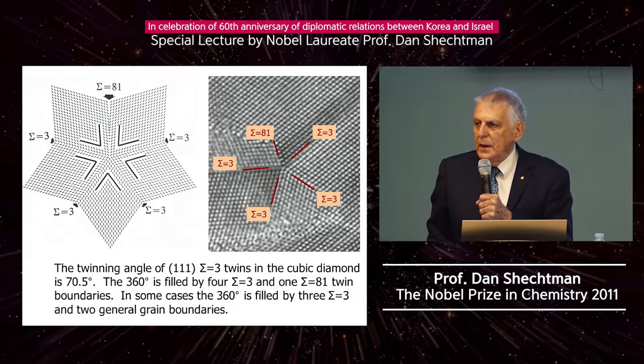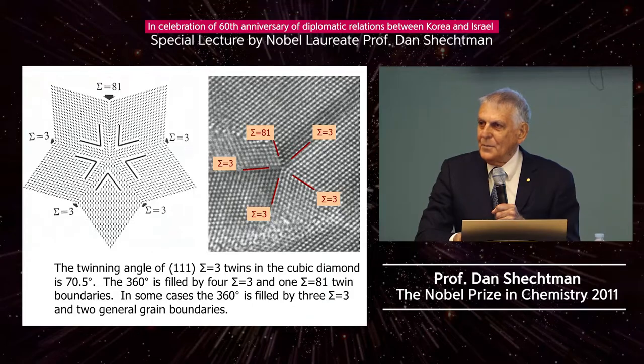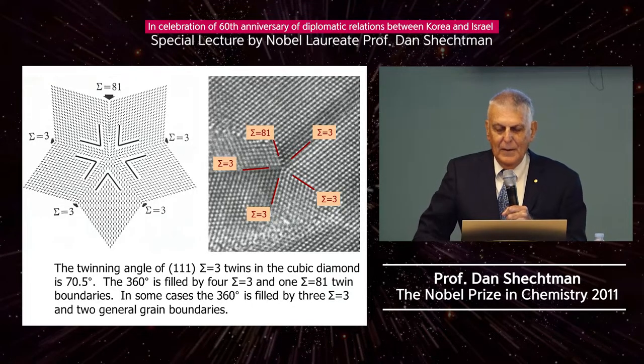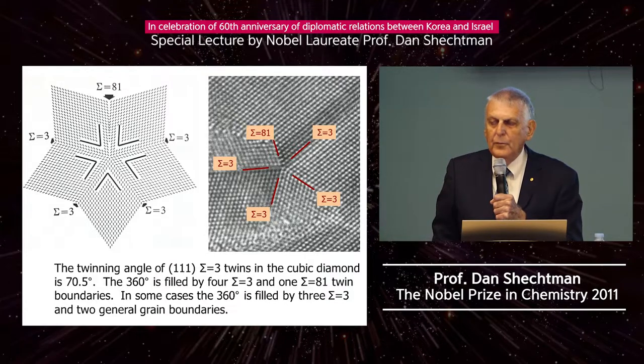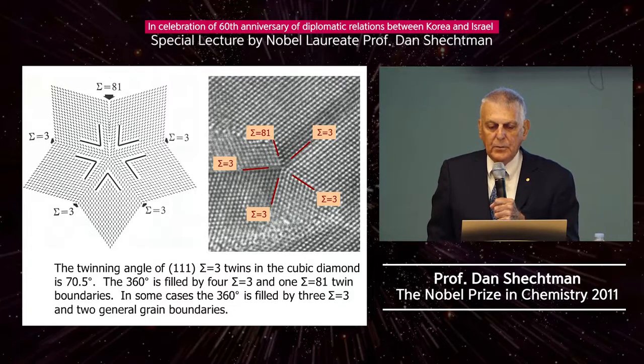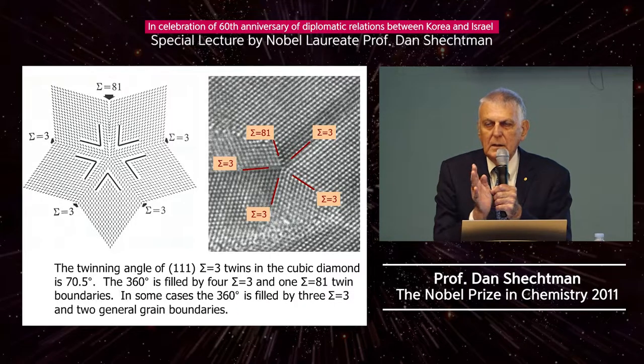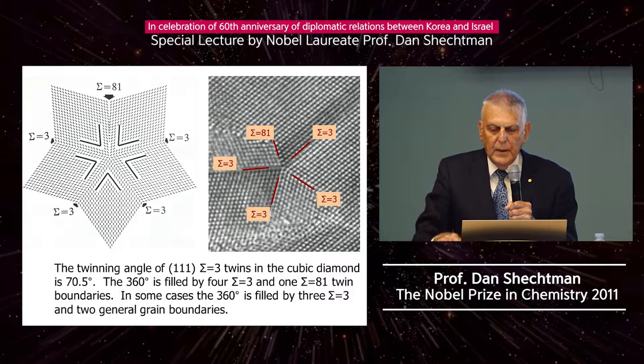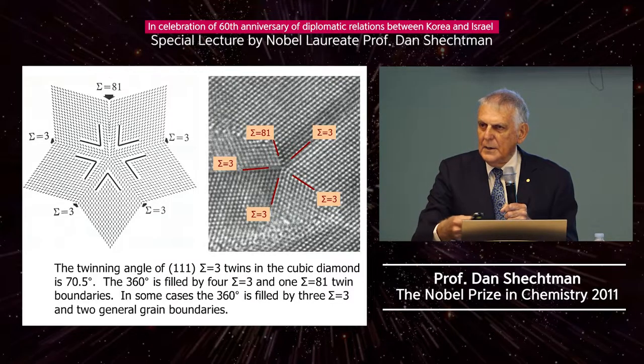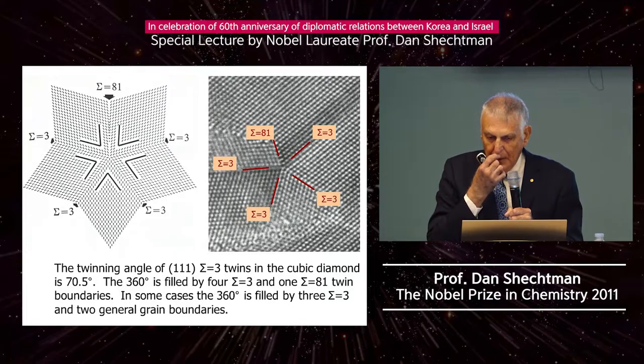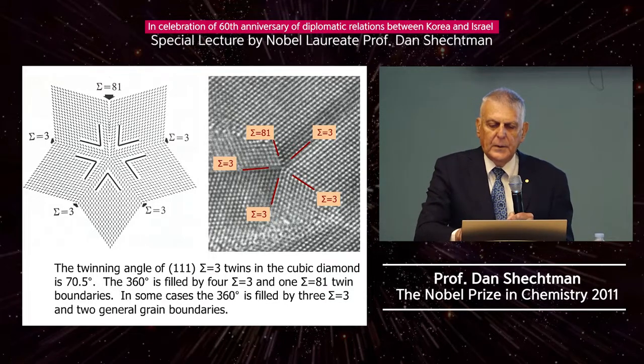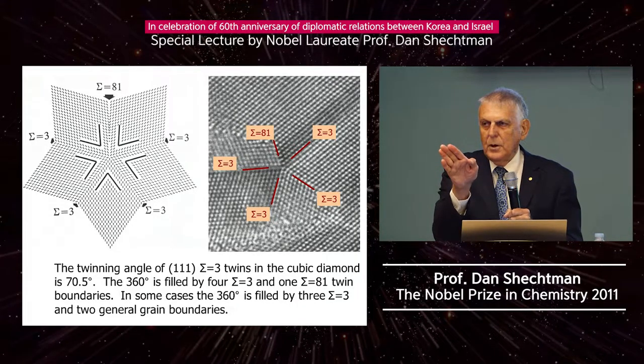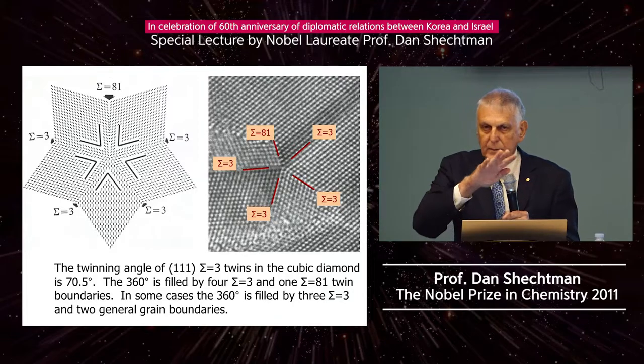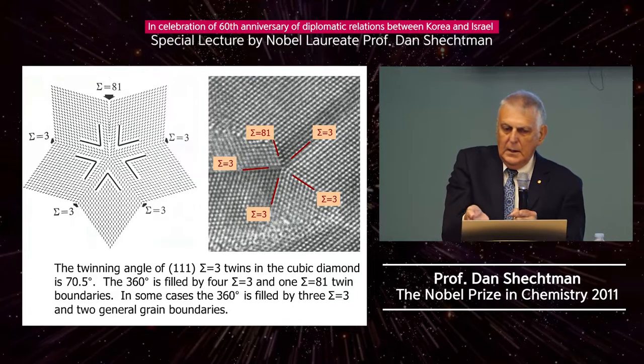Okay, this is what I thought I had. These are twins, not in a quasi-periodic material, these are twins in diamond. But on the right, you see a five-fold twin. These are five crystals that meet at a very special angle, and you can count them, there are five of them. And the sigma notation, forget about the sigma numbers, they're not important now. If you look at the crystal at the top and the crystal on the right, they are rotated 72 degrees to each other. 360 divided by 5, 72 degrees. And then 72 degrees again and again and again.